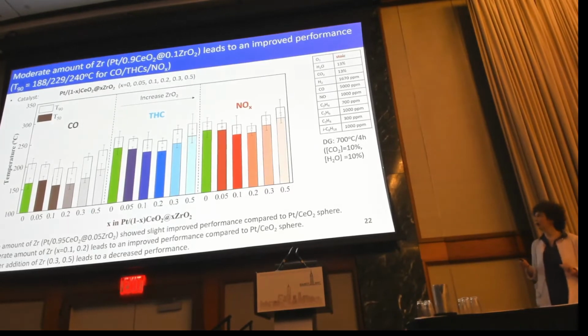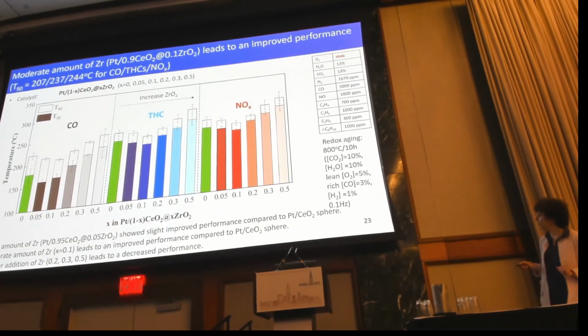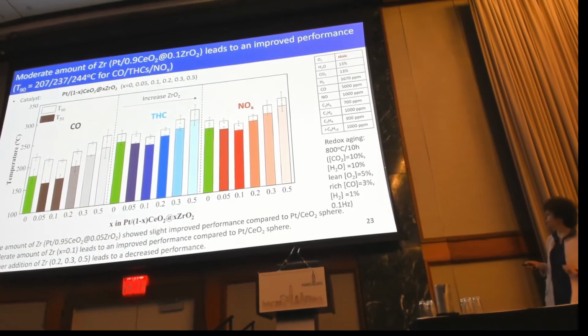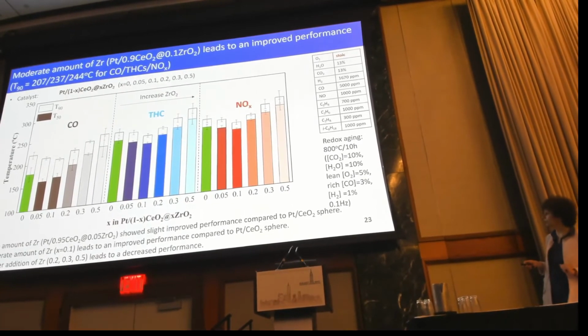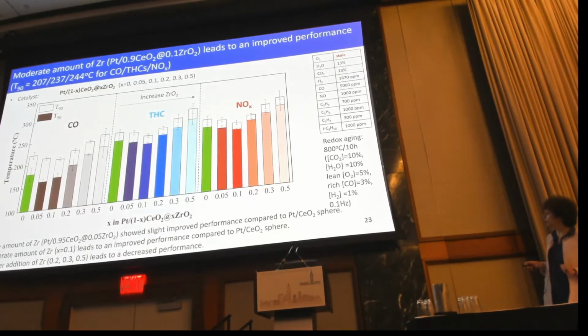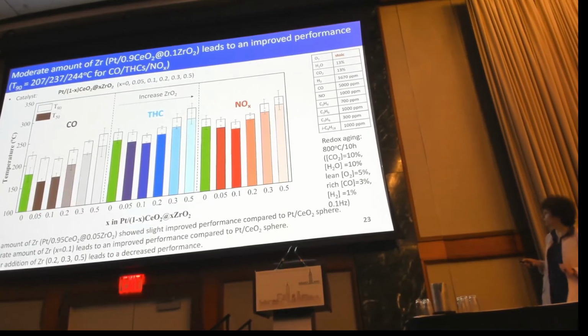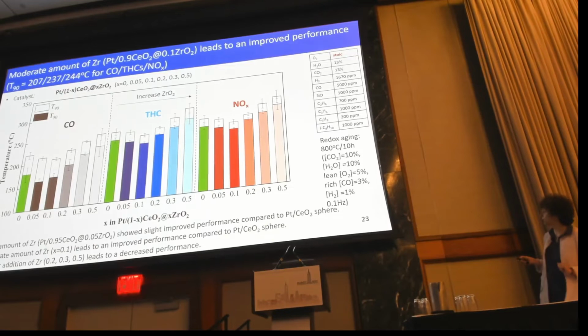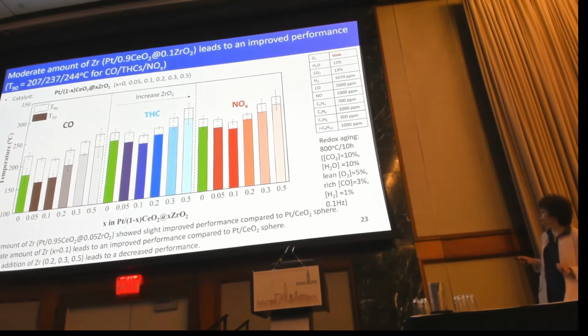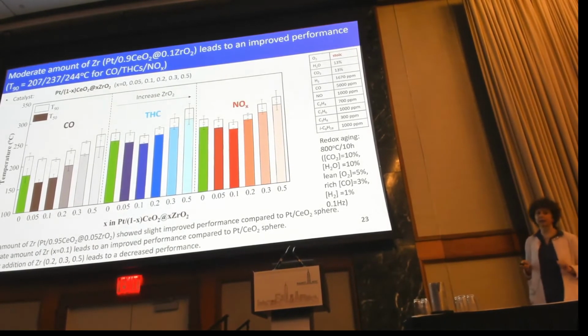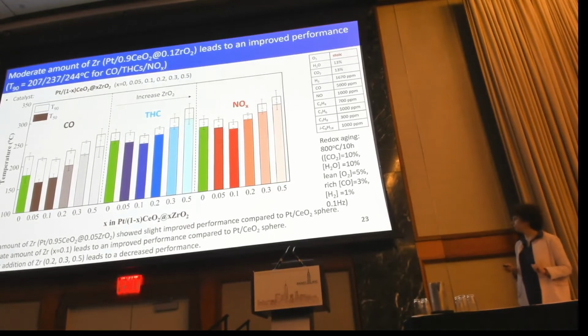So let's see what is the performance after hydrothermal aging. Here you see that after hydrothermal aging, when we add a small amount of zirconium, around 0.05 and 0.1, we see an improvement, particularly here for the total hydrocarbons and NOx. But then if we add more zirconium to the sample, we see that the catalyst does not perform as well.